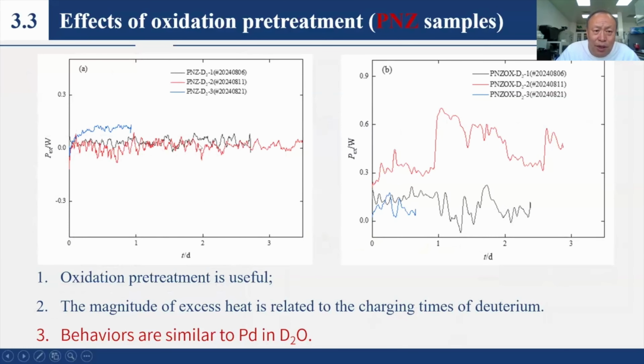This is another experiment for PNZ samples. In the left pictures we can find the black curve is for the first time, the red curve the second time. We can find only the third time using deuterium there is some more excess heat. If we replace the sample with the oxidation pretreatment, there the excess heat appears. The black curve is the first time, the red curve is the second time, and the blue curve is the third time.